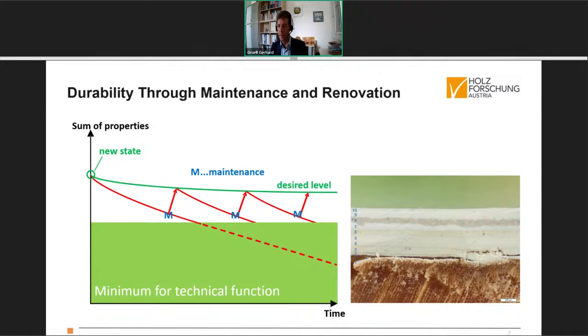And the second factor is adhesion of coating on the substrate or in between coating layers, as you see here. The loss of adhesion here is really a critical problem because you cannot put a maintenance coat on top, which improves adhesion down here. That's impossible. So in this case, in particular because of the loss of adhesion, degradation has already gone down under a minimum for technical function, and we need some other work to be done. We must remove the coating down to the area where adhesion is poor, and then we must renovate, we must repair the coating and put a new coating on top.